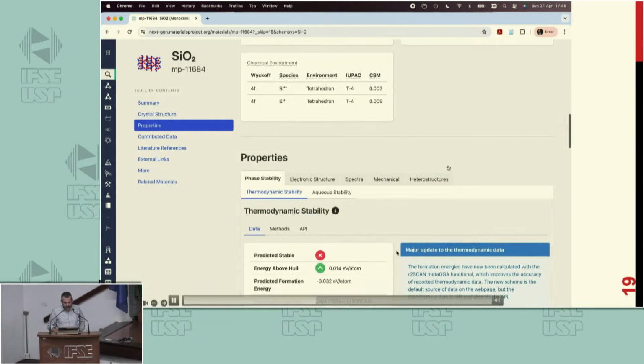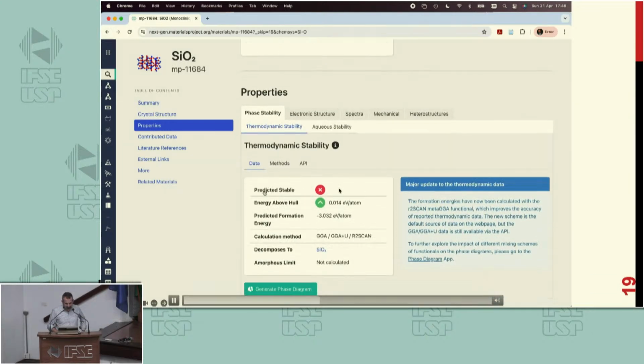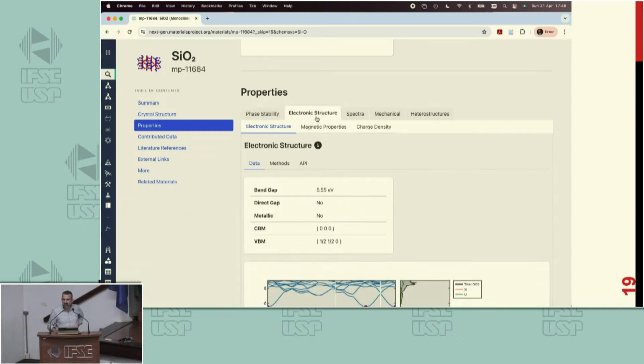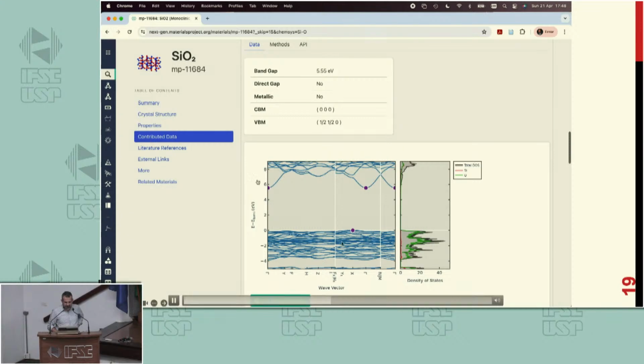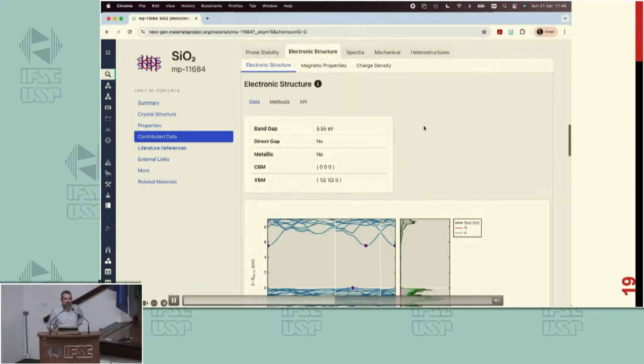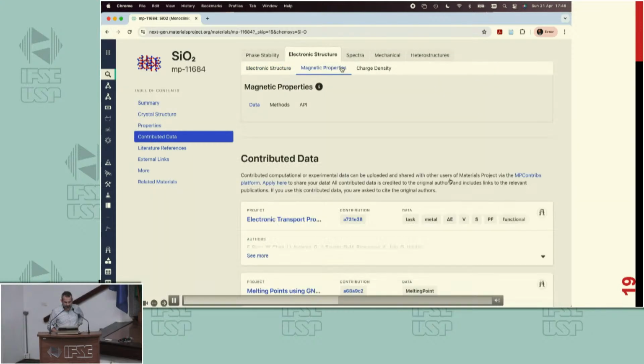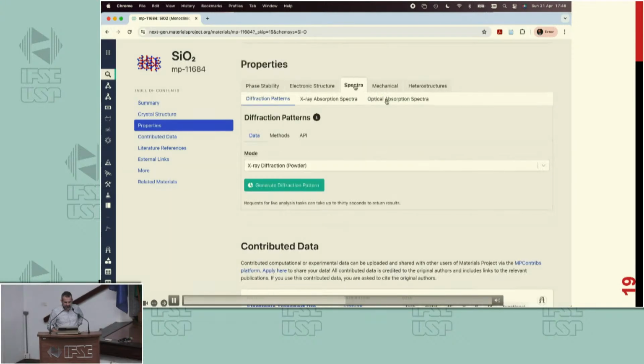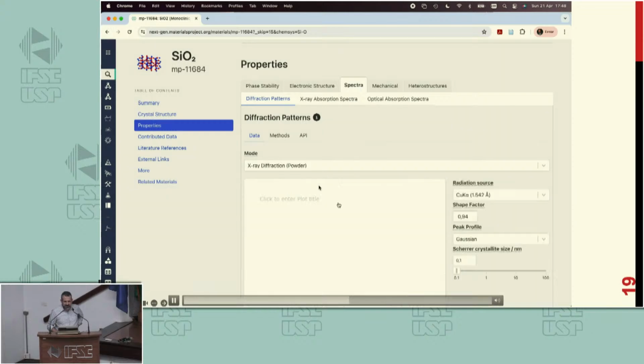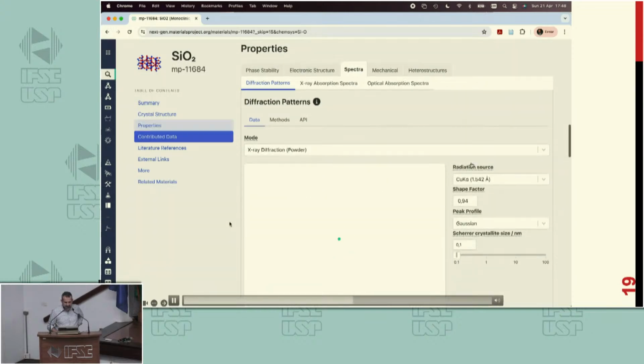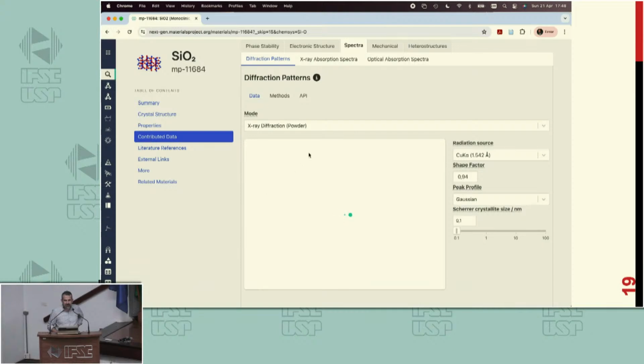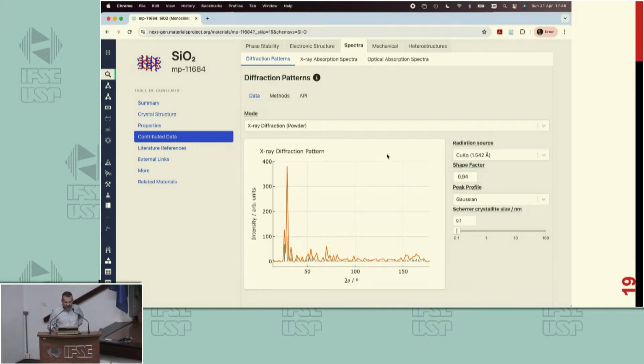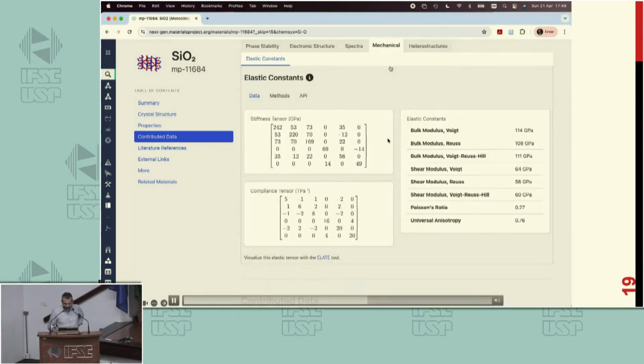All structural properties. Also, predicted stable. So this one, they say it's not stable, so it's calculated, but it's not stable. It shouldn't be synthesizable. This is the band structure for calculating the band gap of the material. Okay, you have magnetic properties, charge density. You have several diffraction patterns. So everything is generated on the fly for 150,000 materials, okay?